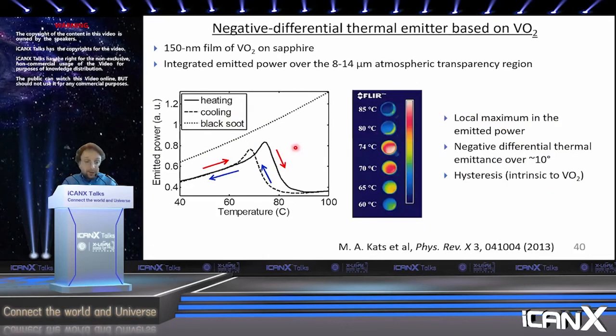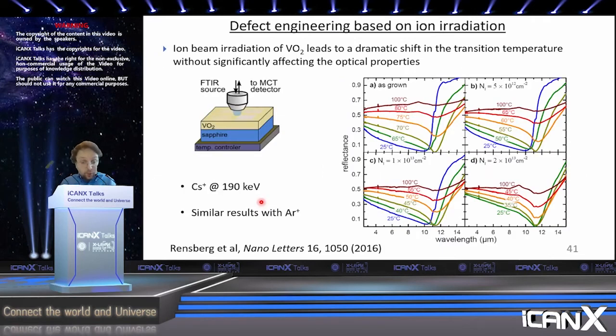So you might notice that this happens at a temperature of about 70 degrees Celsius. That's where the phase transition of intrinsic VO2 is. Now, there are known ways in the literature to tune the phase transition of VO2 by alloying with various materials. We discovered a new way to tune the phase transition of VO2, published in 2016, jointly with Carsten Ronning's group at the University of Jena in Germany. And in this case, what we discovered is that the ion beam bombardment of VO2 can lead to a significant change of the transition temperature.